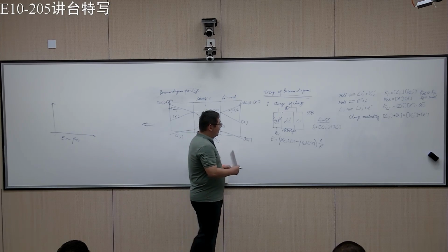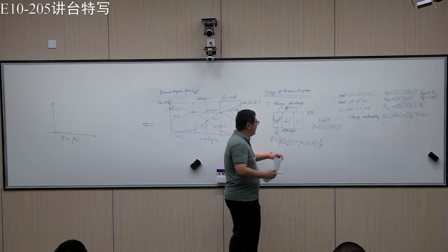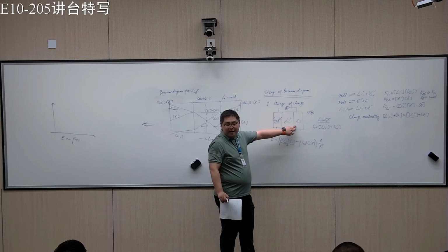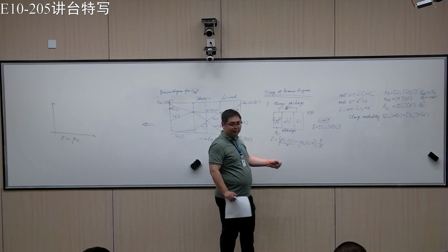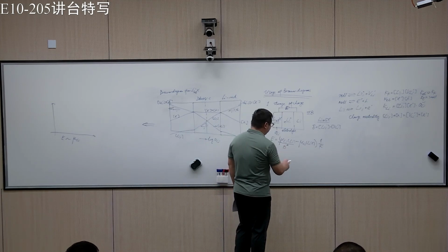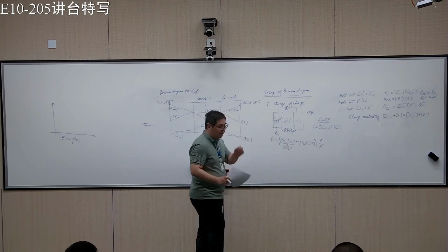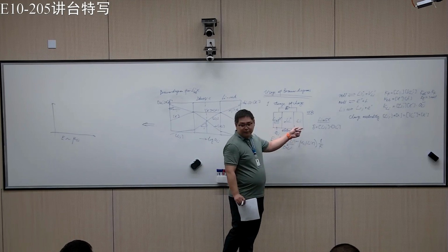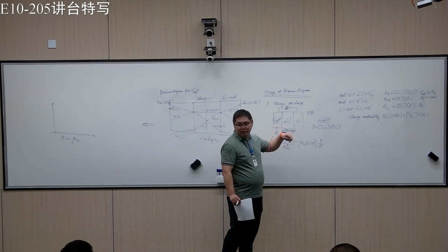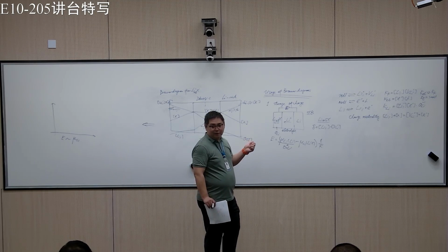However, what you can see here is that because I assume we are using lithium metal as the anode, the chemical potential for any pure material should be 0, so 0 eV or 0 kilojoule per mole. It doesn't really change, right? Because it's metal. You put more lithium into the metal, or you take lithium away from the metal, it doesn't really change its chemical potential.